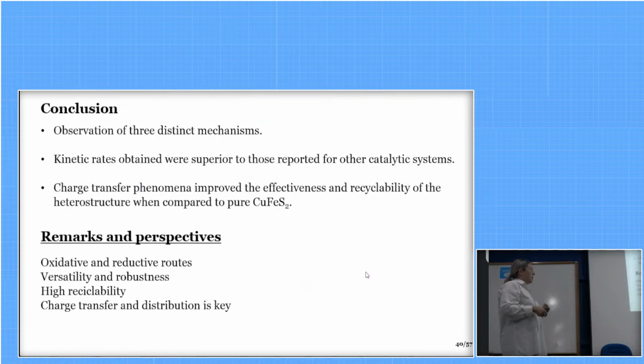Our conclusions are the observation of three distinct mechanisms which show the versatility of the catalyst, that the kinetic rates obtained were superior to those reported for other catalytic systems, and that charge transfer phenomena improved the effectiveness and recyclability of the heterostructure when compared to pure chalcopyrite.